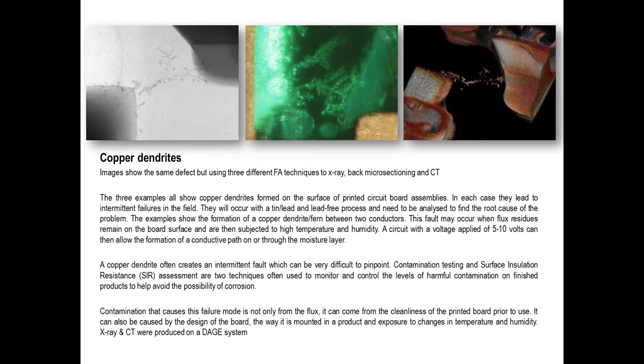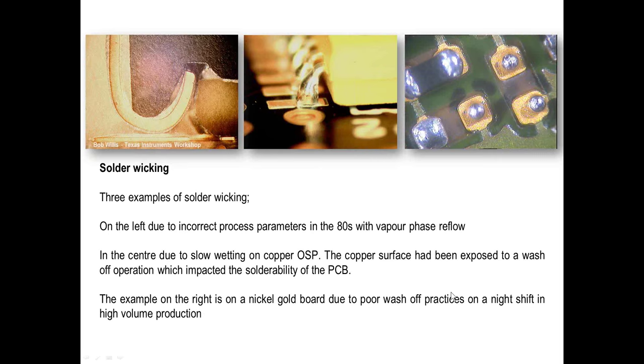But the one in the center, from a failure analysis point of view, you want to do it as cheaply and cost-effectively as possible. So what I've done is I've ground up through the board, like you would a microsection, just below the pads, the back of the pads on the laminate surface, and I can optically see the dendrite formation. And that's nice because, again, it's a more cost-effective piece of failure analysis that other engineers could do in their own facility.